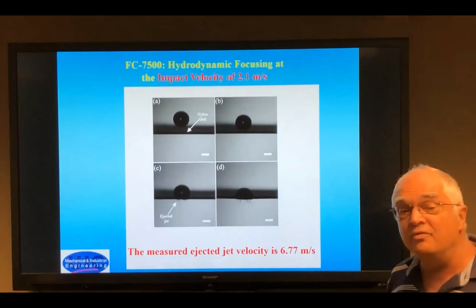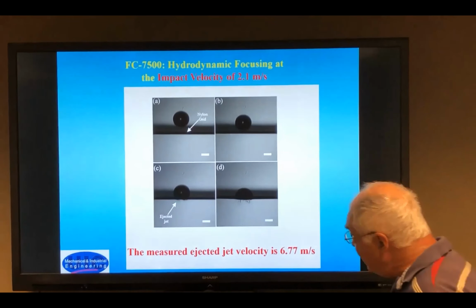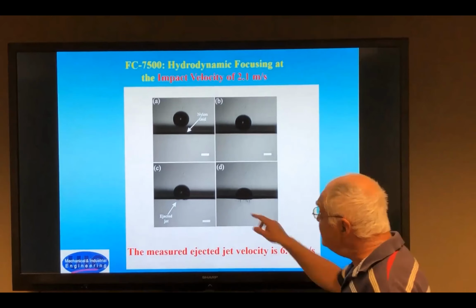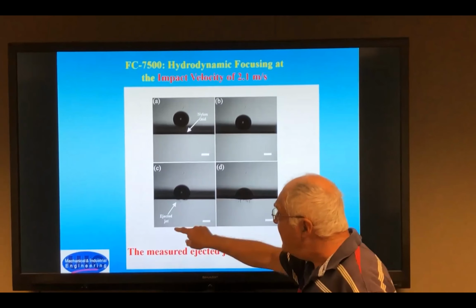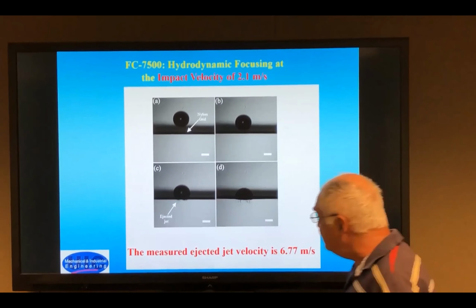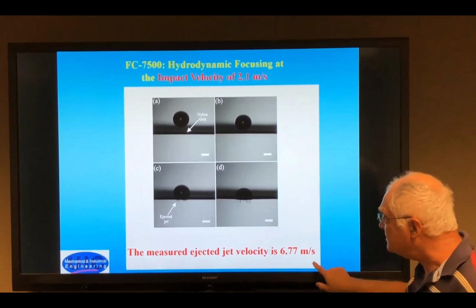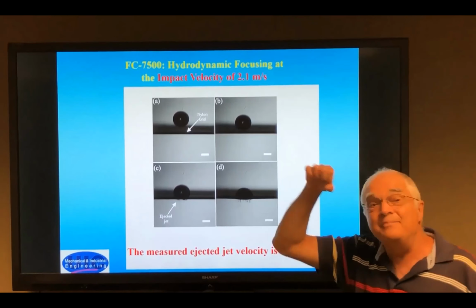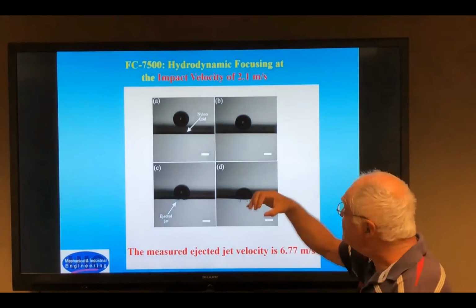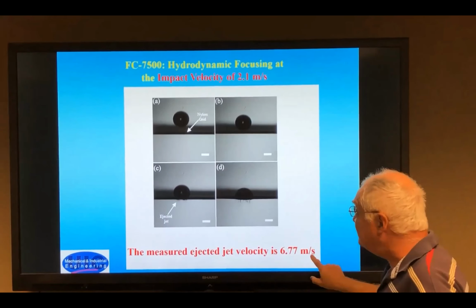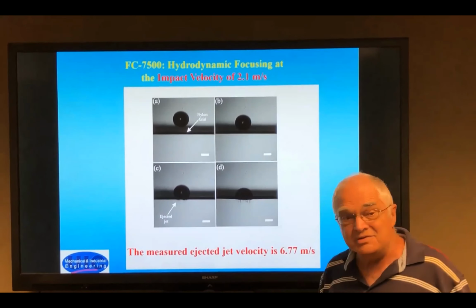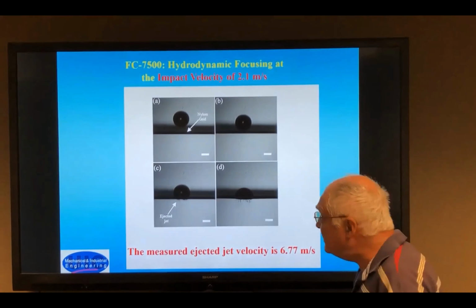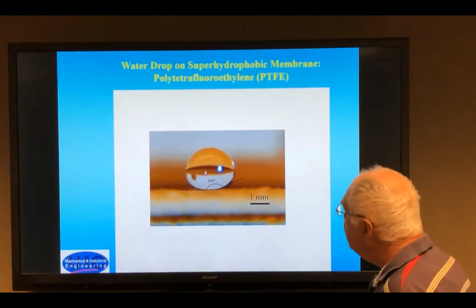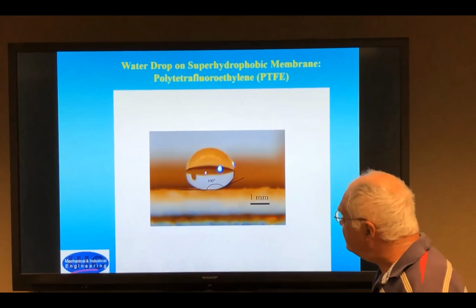Now, is it possible to prove that what I'm telling you is true? Yes, that's a direct measurement we did. You see here some individual jets coming from the membrane pores, and we can measure the velocity of these jets. What is interesting is that the measured velocity of this jet is higher than the impact velocity. Even though you dissipate a lot of energy during flow in the pores, the ejected velocity is still higher than the injected velocity. That's exactly the result of the hydrodynamic focusing.